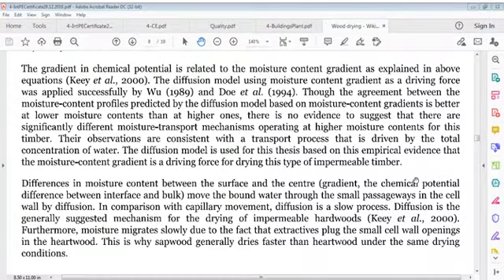Gradient in chemical potential is related to moisture content gradient as explained above. Diffusion model using moisture content gradient as a driving force was applied successfully, though agreement between moisture content profiles predicted by diffusion model based on moisture content gradients is better at lower moisture contents than at higher ones. There is no evidence to suggest that there are significantly different moisture transport mechanisms operating at higher moisture contents for this timber. This observation is consistent with a transport process that's driven by total concentration of water. Diffusion model is used for this thesis based on this empirical evidence that moisture content gradient is the driving force for drying this type of impermeable timber.